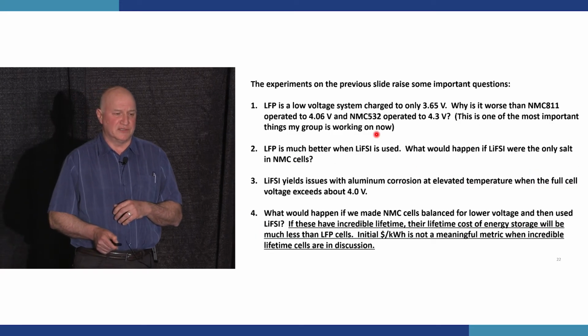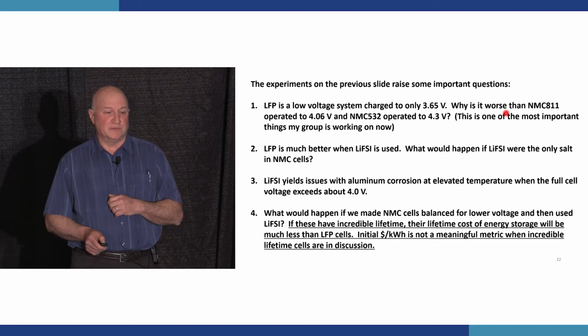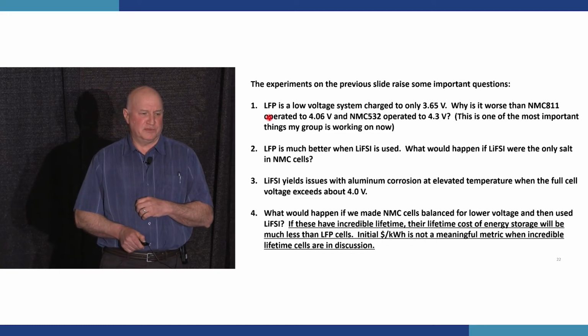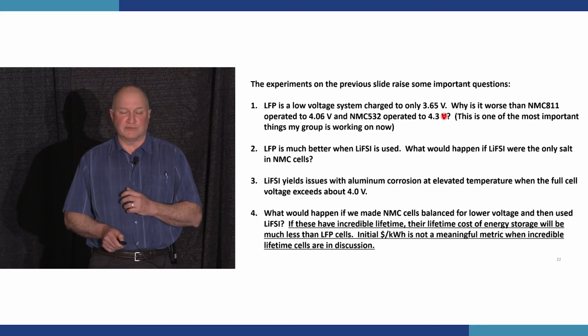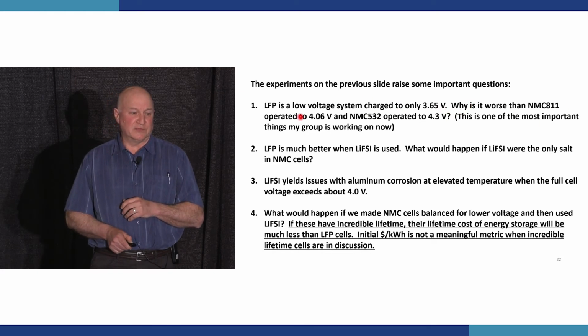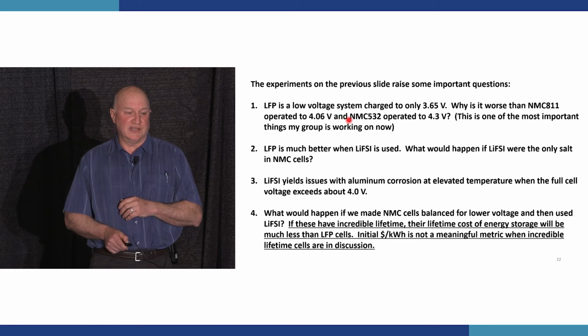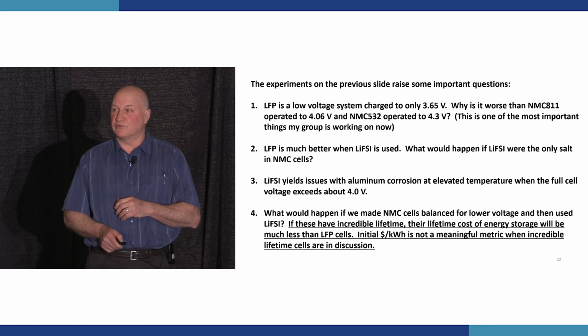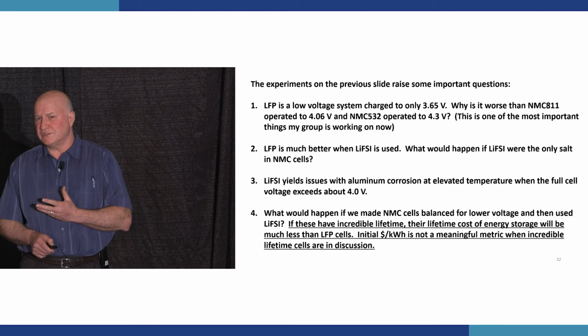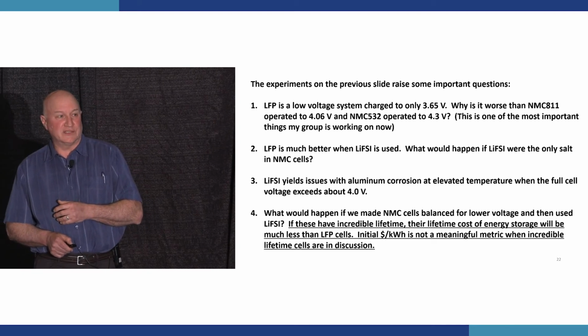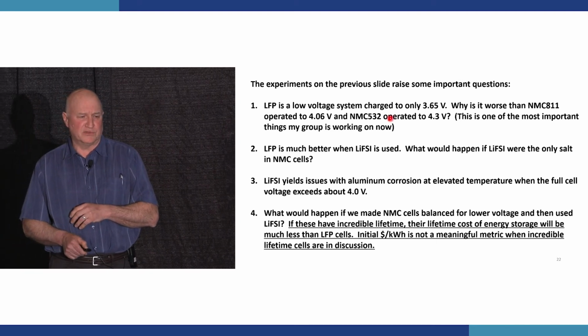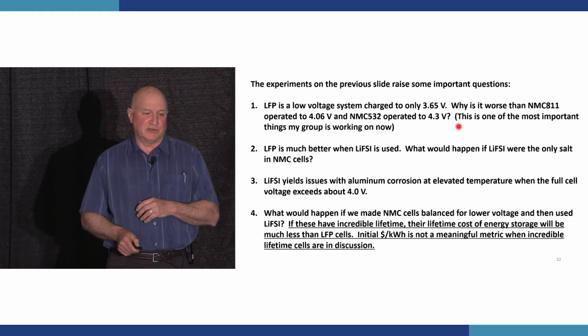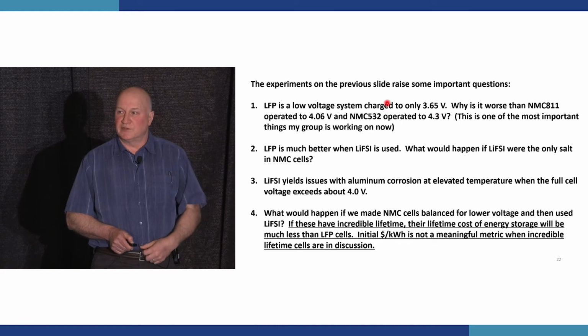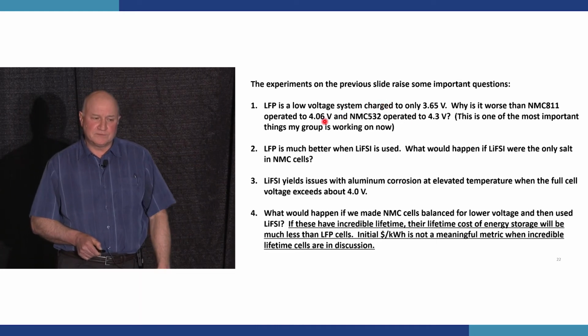So the experiments on this previous slide raised some very important questions. LFP is a low voltage system charged at only 3.65 volts. Why is it worse than NMC 811 operated to 4.06 volts and NMC 532 operated to 4.3 volts? At these higher voltages, the reactions between the electrolyte and the charged electrode materials should be much more severe than in the case of LFP. So this actually is one of the most important puzzles that my group is working on at this moment.